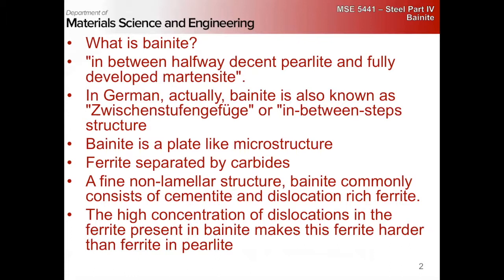There's a shear that happens, which gives rise to a large stress, right? You can imagine if I have a lattice that suddenly goes like this, it's like a 12% shear, whereas elastic strains are typically on the order of 0.2%.